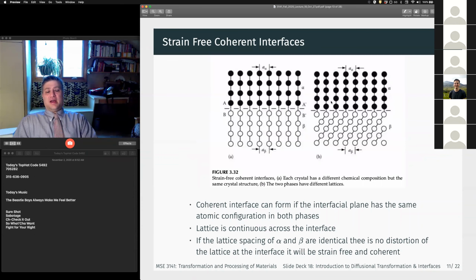Okay, so if we have a phase alpha and a phase beta that have the same lattice separation, right? We have our planes that are approaching this interface. If they have the exact same separation, there can be a one-to-one correspondence. We can have perfect bonding across this interface, right? And we now have a strain-free, perfectly coherent interface, right? Coherent means that there's a one-to-one bonding, right? So the local neighborhood isn't altered across the interface. It's just that instead of bonding from an AA, we're now doing an AB type bond, right?